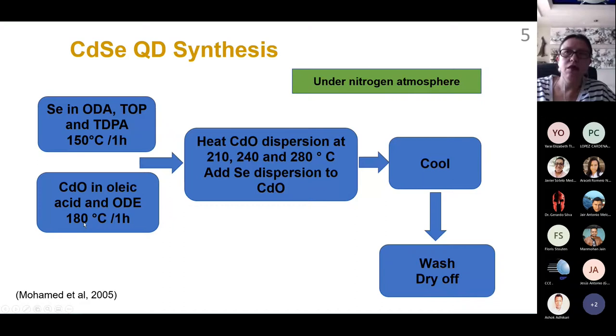180 Celsius degrees. For the synthesis, we inject the selenium dispersion inside the cadmium oxide dispersion at a specific temperature. In this case, we use three temperatures, 210, 240, and 280 Celsius degrees, for three different syntheses. At this temperature, we carry out the synthesis for 5 minutes and then cool it, and when we get to 60 Celsius degrees, we put in the nitrogen atmosphere, and